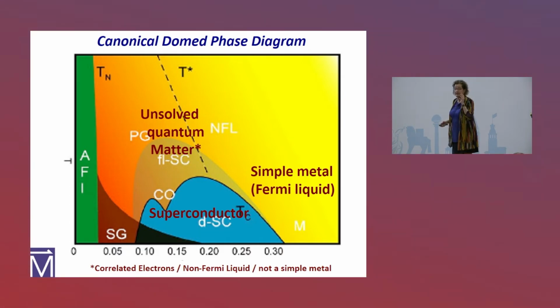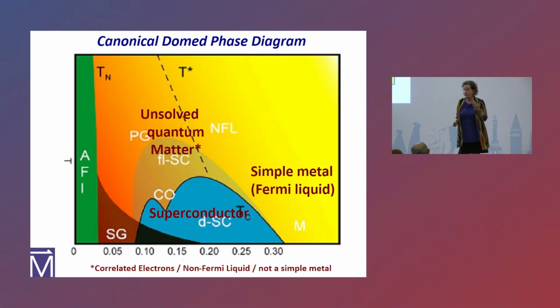But in any case, on the low pressure, ambient pressure, low doping side of the phase diagram, you typically have an antiferromagnetic insulator. Over on the right-hand side, you typically have a Fermi liquid. And when they cross over, in almost every case, above the superconducting dome that I mentioned earlier, you have what I call unsolved quantum matter. Again, the devil is in the details. Whether it's nematicity, stripes, whatever, or the pseudogap, we don't really understand all this. But what I will say is that's where the interesting part is. If I get time for my analogy, I'll say this later. For those of you that have ever taken solid state physics, you know that we know how to solve Fermi liquids, right?